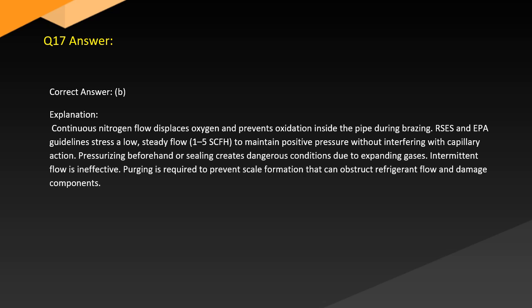Answer. Correct answer. B. Explanation. Continuous nitrogen flow displaces oxygen and prevents oxidation inside the pipe during brazing. RSES and EPA guidelines stress a low, steady flow, 1–5 SCFH, to maintain positive pressure without interfering with capillary action. Pressurizing beforehand or sealing creates dangerous conditions due to expanding gases. Intermittent flow is ineffective. Purging is required to prevent scale formation that can obstruct refrigerant flow and damage components.